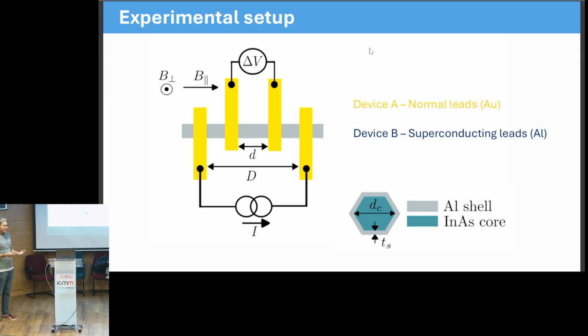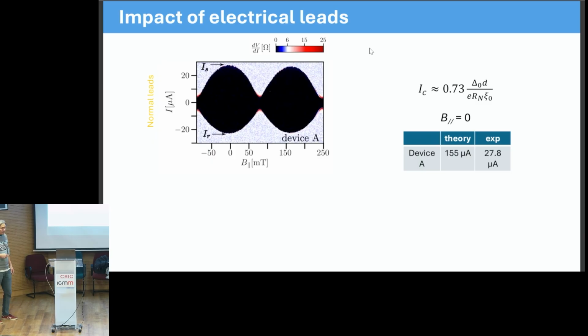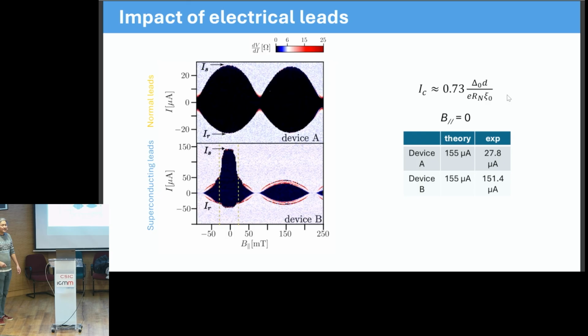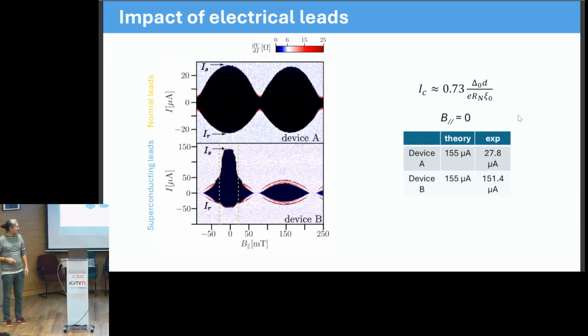The measurement, this is our transport measurement, so we're measuring the resistance of the wire. And when we characterized both types of devices, we saw a very strong impact of the type of the electrical contacts, as I mentioned before. So if we measure with gold contacts, as was done in the previous paper, we also see that our critical currents are much lower than the one expected from pair breaking. But when we study similar devices now with superconducting contacts, the critical current we measure really is comparable or almost the same as one would expect from theory.